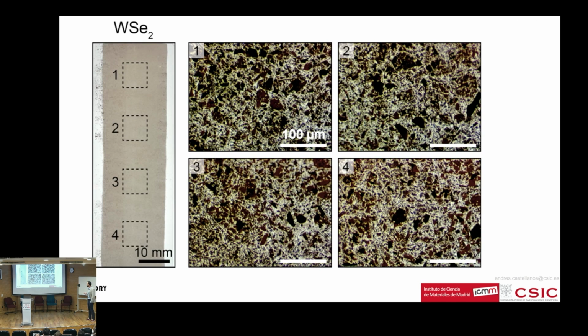When you take a look in the optical microscope, you see that this is not just a single crystal covering the whole tape. It's a network of flakes. There is a little bit of touching, a little bit of gap between some of the flakes. So it's almost complete coverage, typically around 90% coverage, something like 80, 85, 95, depending on the starting conditions and how much you do the rolling, et cetera.